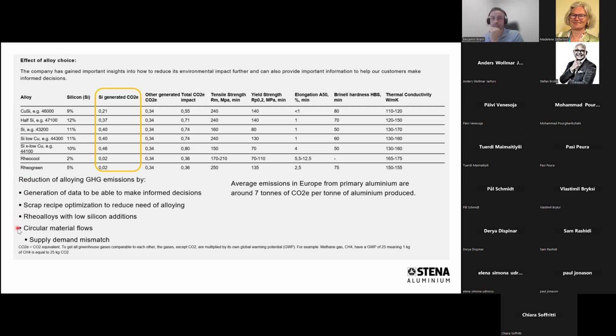Circular material flows is, of course, something which is talked a lot about, and we are working with circular material flows as well, and these kind of closed loop solutions, and we're always looking for more of those kind of solutions as well. What is kind of important also to mention is that there is, of course, even though we are working with a lot of these closed loop solutions and circular material flows, there is kind of a supply and demand mismatch, obviously, here when we look at the silicon addition. So it's difficult to, for instance, produce 46,000 alloy with only 46,000 scrap. So there is always a bit of a mismatch, both in the compositions of the scrap and the compositions of the alloys, and also in the quantities of the different scrap types and alloy types that the customer wants.